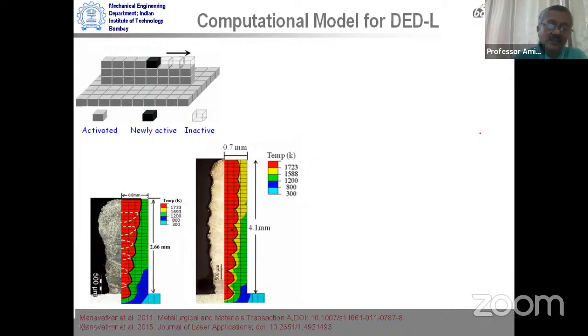So we see that the kind of model is able to predict what is going to be the shape of the part. And it shows that if we can do it better, perhaps we get a more uniform wall thickness. And if we can optimize this by the model itself, it can perhaps save a lot of trial and error tests with very costly powders.